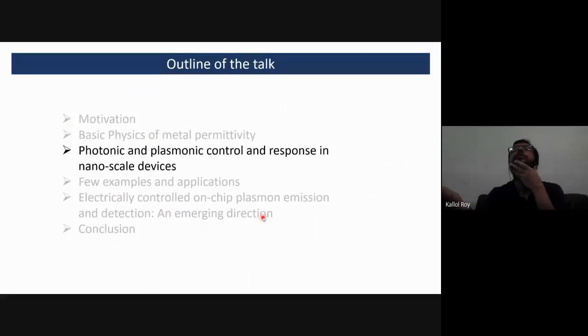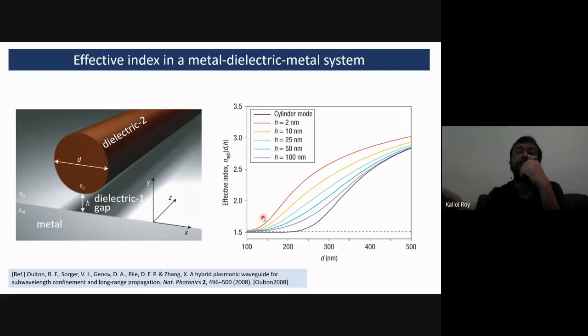So let's look at a few examples of control via specific device design in nanoscale. This is one of the famous metal dielectric systems, which shows that the effective index can be controlled. For example, you see there is a dielectric rod which has a dimension of d, placed on top of metal by a small gap filled by another dielectric. The effective index of this system changes as you change the gap. Say, for example, here it's tuned from 2 nanometers to 100 nanometers, and hence the effective index changes drastically.